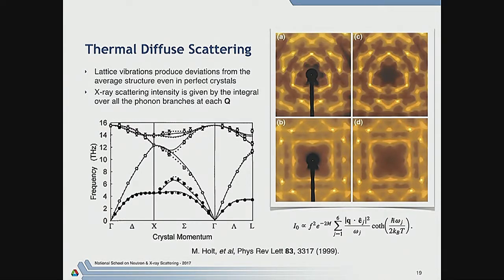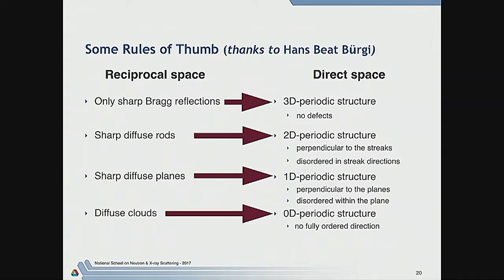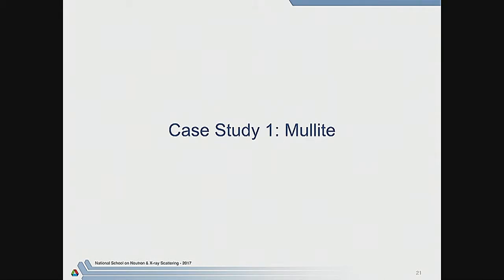So you have dispersion relations. The different intensities of the diffuse scattering are then going to have a term from the frequency and from the temperature dependence, etc. And even in a perfect crystal, you can actually use it to analyze the phonon spectra. I realize I'm probably talking a bit too long, so I'm going to flash through this. But these are just some rules of thumb, which basically reflect the fact that all diffuse scattering is a Fourier transform. So if you have rods of scattering, that means you have planes of disorder. And we'll see examples of that later, so just have that as a reference.